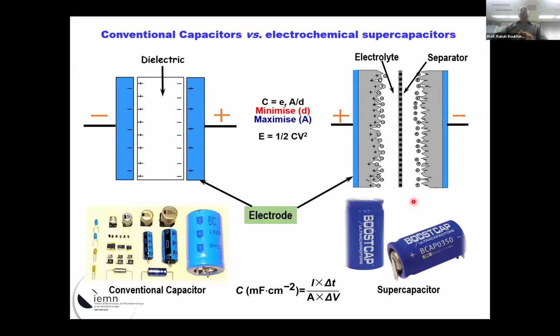Okay, so I will not spend too much time on this, but what's important is, if you want to increase the energy, you have to increase the operating voltage and the capacitance. For the capacitance, what we do now with supercapacitors is use a high surface area, but you have to have very good control of the pore structure, so that you can accommodate the anions and cations. Otherwise, you will be just using the surface and not the full surface area.